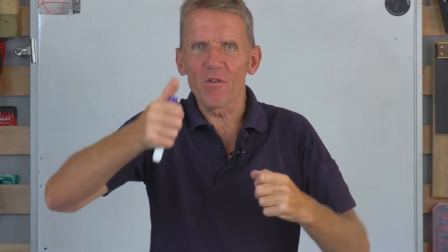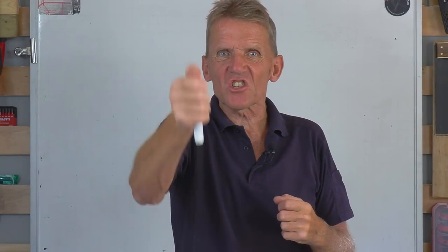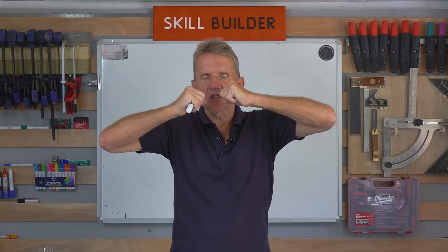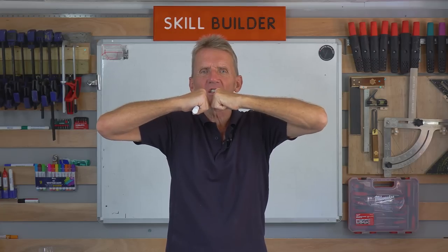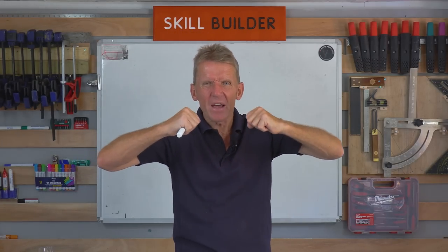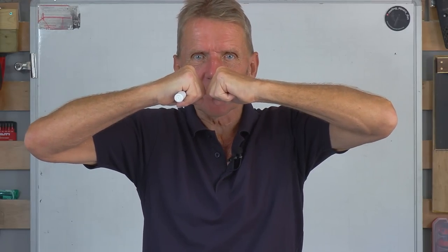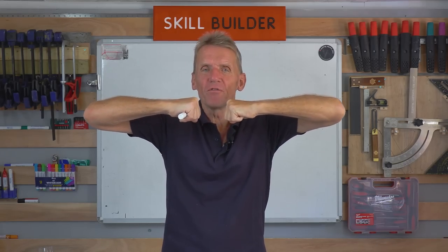What will happen then is that if you filled them, if you've been around and you've diligently pointed up as that surveyor suggests, you will find that as it tries to close up, it will push against your hard sand and cement that you've put in because you're always going to put in a nice strong three to one mix. You put your three to one mix in, the building is trying to close up, it can't close up and it just pushes it further apart.